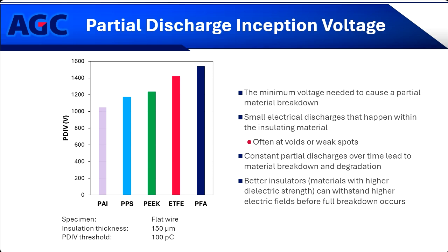The next thing I want to talk about before we actually start to look at the data on this graph is that PDIV measurements are very specific to how they're measured, the form of the sample that you are testing, the atmospheric environment that they are tested in, as well as the instrument itself. One PDIV tester is not going to be the same as your neighbor's PDIV tester. They can analyze and detect the data in different ways. Some are more consistent and accurate than others.